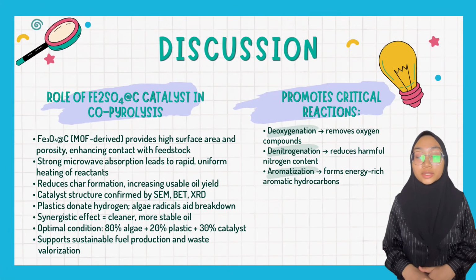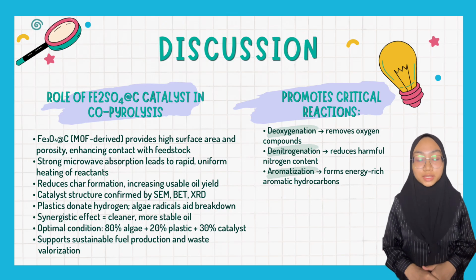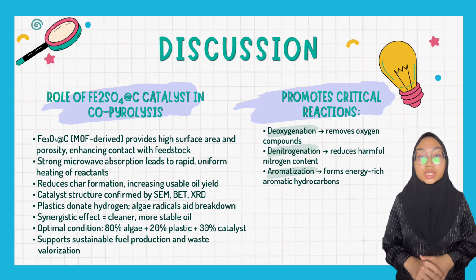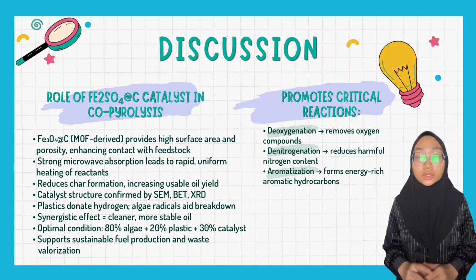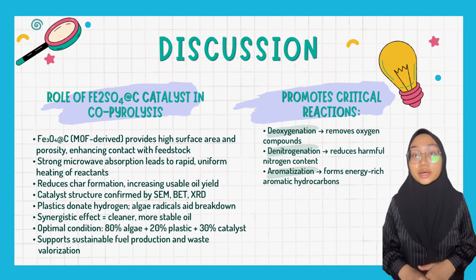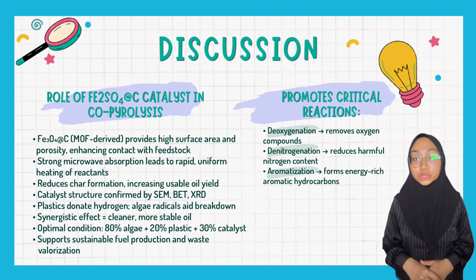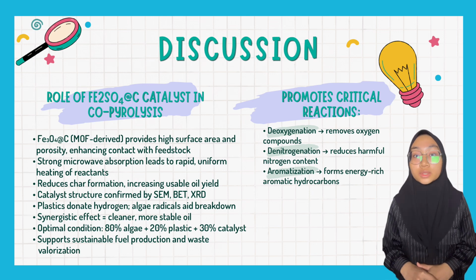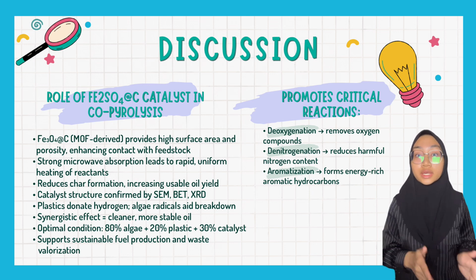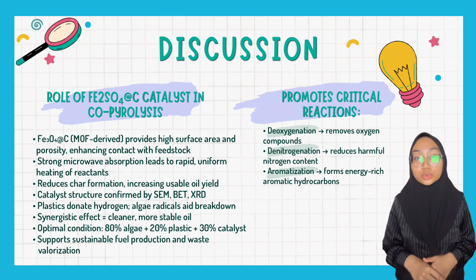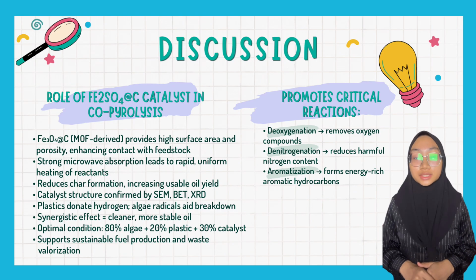The ferrum oxide at C catalyst plays a key role in making the co-pyrolysis process more effective. Firstly, because it derives from metal organic frameworks, it has a high surface area and porous structure, which allows better contact between the feedstock and the active site. This improves the overall conversion efficiency.